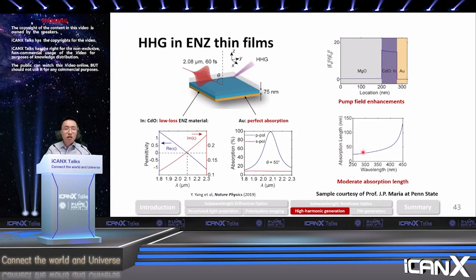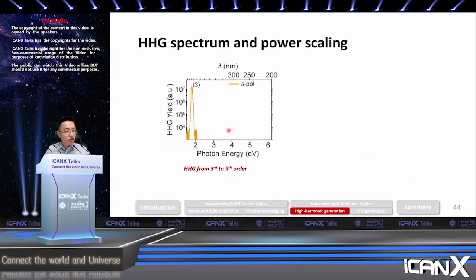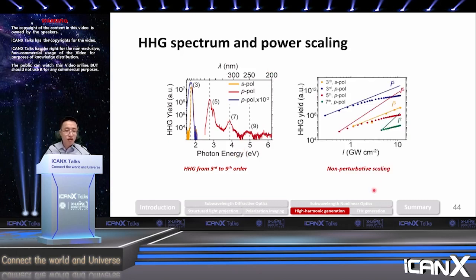In the experiment, we first use S-polarized light to shine on our sample. In this case, we are not exciting the ENZ resonance, so we only get the third harmonic generation. Then we change our pump polarization to P-polarized light, and we see high harmonic generation all the way from the third to the ninth order. We also see that this process becomes non-perturbative in scaling, meaning that, for example, our third and fifth harmonic generation doesn't follow the rule of I cubed and I to the fifth.